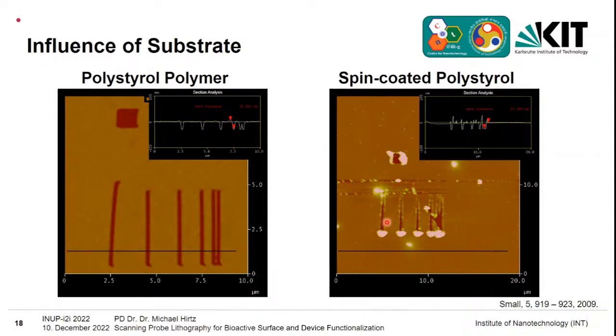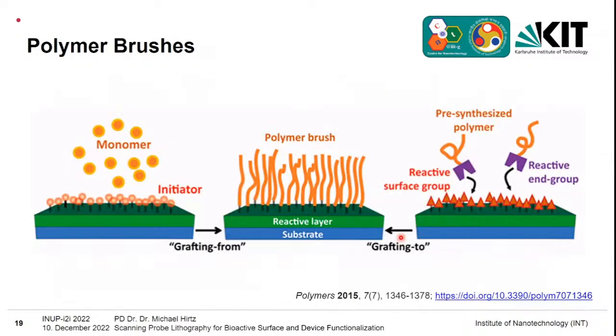So what makes this difference? Why is this giving you clean lithography? And here you have this kind of widening of the lines. For that, I would briefly show you what polymer brushes are. A polymer brush is basically similar to a regular polymer, but instead of the polymer chains being just entangled with each other, a polymer brush is bound to the surface, where each of the polymer chains grows either from the surface or, when it's pre-synthesized, is grafted to the surface.